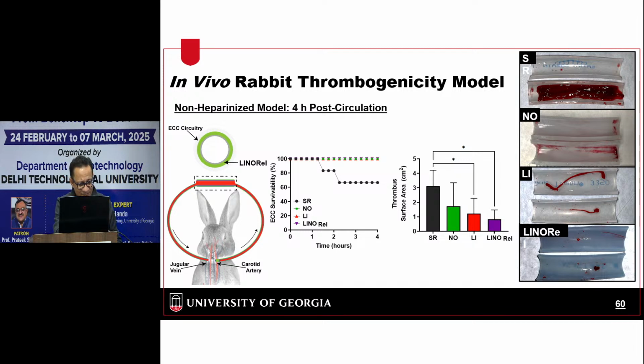By itself, if you see this graph, silicone rubber tubing, only 60-65% of the tubing survived. Like by 2 hours, some of the loops actually clotted. The flow rate went to 0. But NO, liquid infused NO surface, they all survived the full 4 hours at least.